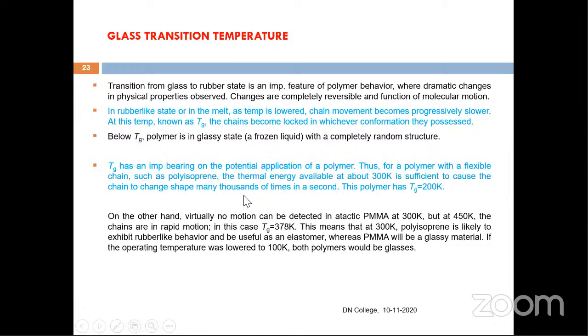For example, you take the case of polyisoprene. Take the rubber, that is the polyisoprene, the natural rubber. It is a flexible chain, and this is at room temperature, 300 Kelvin. So it behaves as rubber because the chain of that polyisoprene can have many conformations, 1,000 conformations within a second. So it's so flexible at room temperature. Its glass transition temperature is around minus 70, 80 degrees centigrade. So at room temperature polyisoprene behaves as rubber because the chain can have so many conformations within a second. So it's an elastomer, a good elastomer.